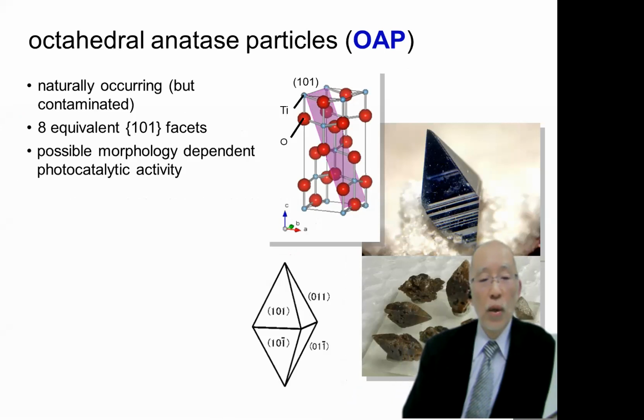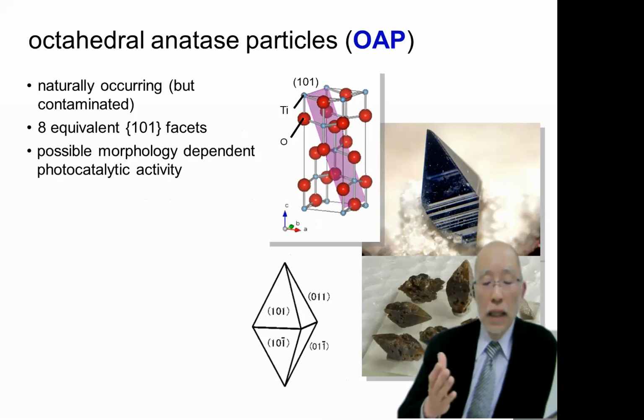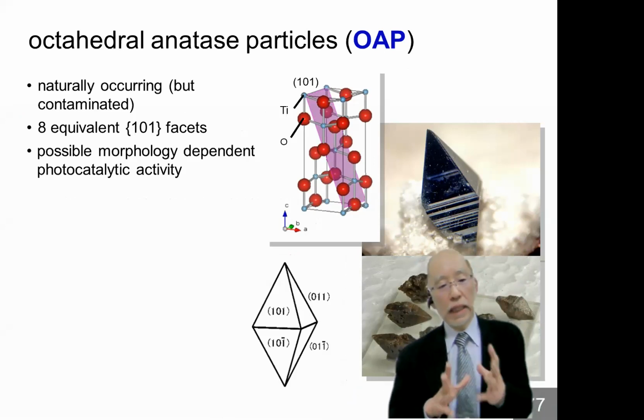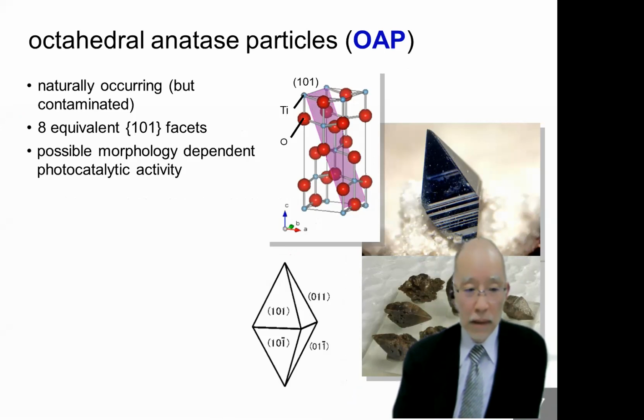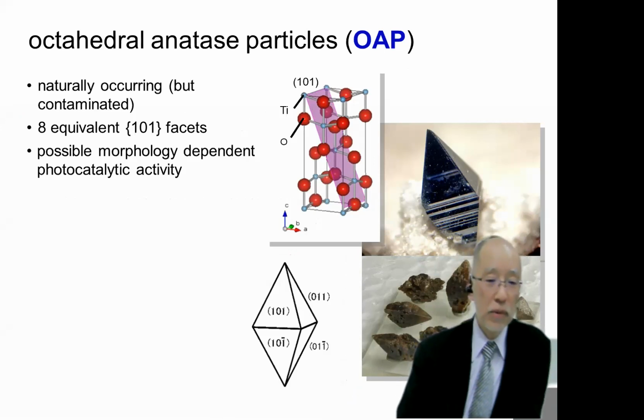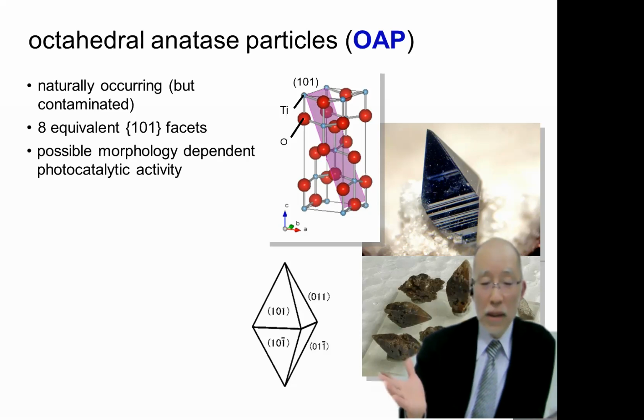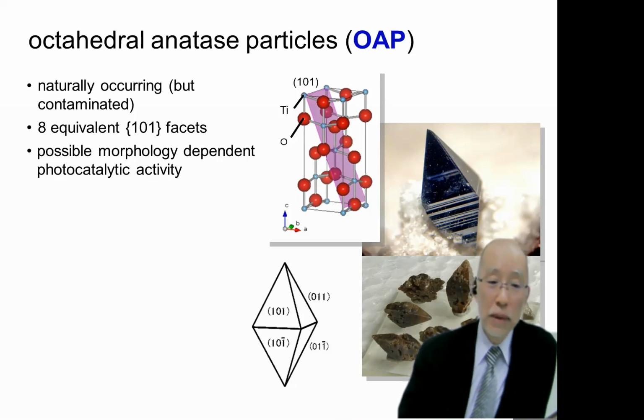Yes. So then, one short story. We have succeeded in specifying the sample. And as you see, we can specify mixed material. For example, anatase and rutile are mixed. Those samples can also be measured. That is, we have some fingerprint of those mixtures. And please remember that for organic compounds, identification is made for pure materials, not mixed ones. For mixed material, it is impossible to identify using fingerprint or other techniques. But for solid material, even for mixed material, that can be done.